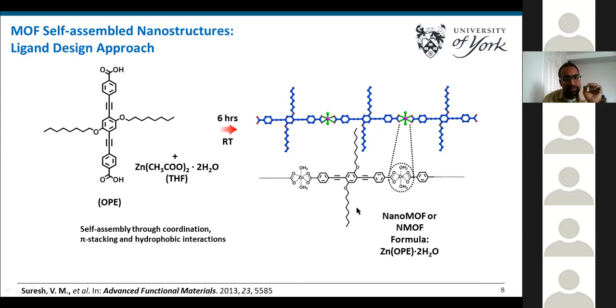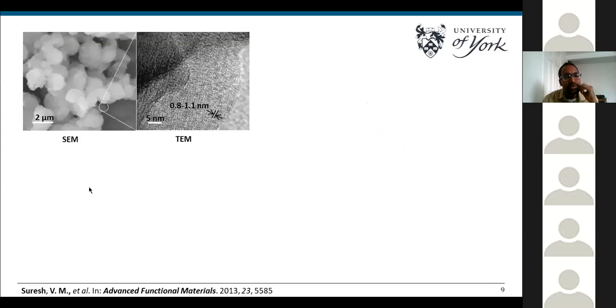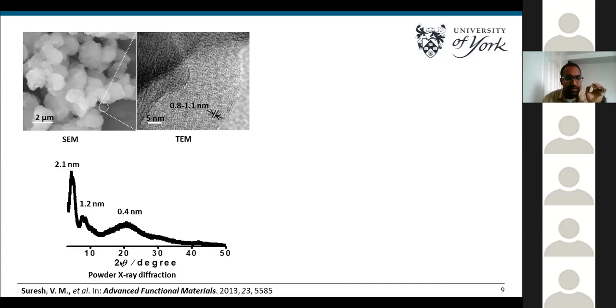These colloids we characterized through scanning electron microscopy. Under the microscope, we see agglomerated particles in a spherical shape. When these particles are magnified under TEM, we see a large number of dark lines separated by a distance of 0.8 to 1.1 nanometer. And in powder X-ray diffraction, we see only 3 peaks, which suggests an ordered pattern. From the TEM and powder XRD, we try to come up with a structure for the nanoMOF.